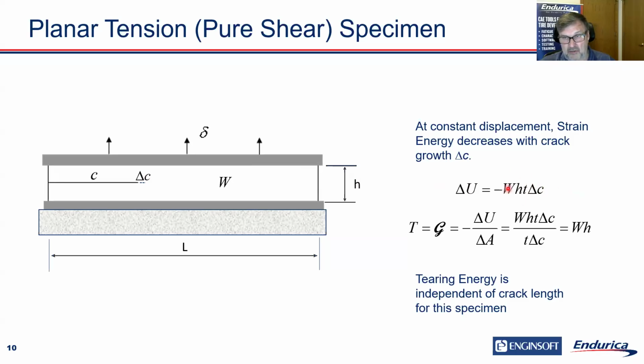And then I multiply that volume times the strain energy density, and I get the total change in the energy. The change in the crack area then is just delta C times the thickness. So I plug those in, I cancel out the T's and the delta C's, and I see that the tearing energy or the energy release rate is simply W, the strain energy density in this homogeneous region, times the original height, H. And it's good to acknowledge that in this specimen, the tearing energy is independent of crack length. So when we use this in experiments, we can directly change the tearing energy level just by changing the strain in the specimen, and it doesn't matter what the crack length is.